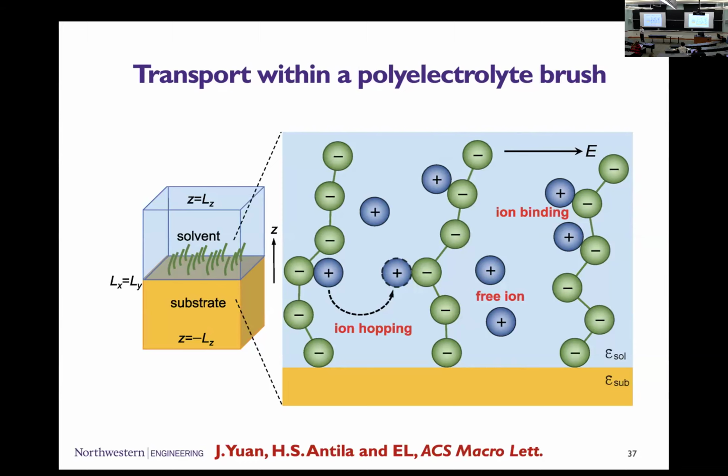I don't think that we have looked at it. I'd be very surprised if they're locked in place, because if you think of those chains, right, they are kept apart by the fact that the equatorial region is repulsive to any other equatorial region. If you turn that off, there's no reason for them to remain locked in place, right? Everything is completely mobile at the surface. Yes, it has to depend on the rate at which you change things. But I think even if you go to the limit where you do it very quickly, you just turn off all electrostatics, or at least the dielectric part, I'm convinced it will just relax. Yeah, I'm certain. There's no reason I can tell that keeps this kinetically trapped.